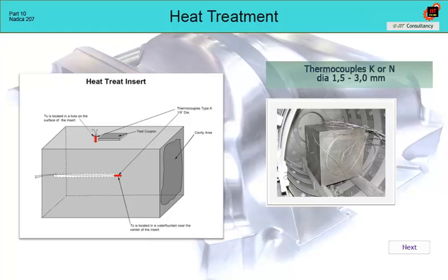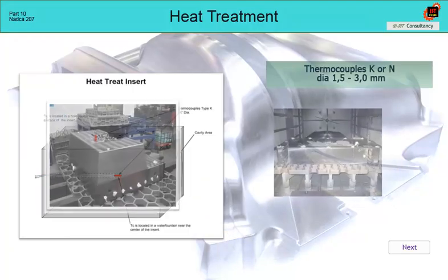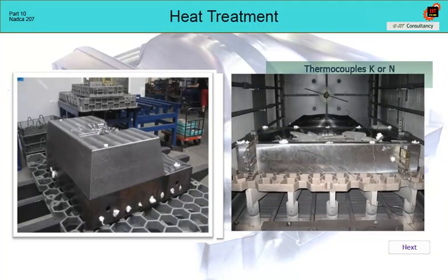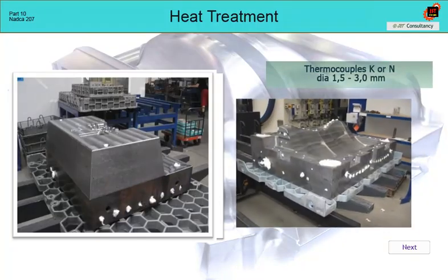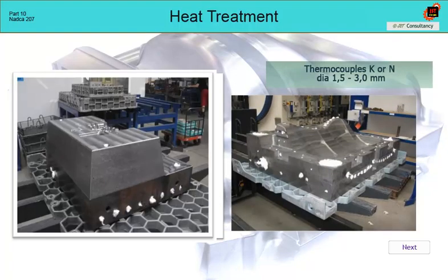A simpler situation is with the thermocouple TC, which measures the temperature of the center of the die. Usually, cooling channels or other auxiliary openings directed to the center of the part are used, but it must be ensured that in the case of a through hole, cooling gas does not flow through this hole. Glass wool, Sibral, or similar heat-resistant material is used for sealing. It must also be ensured that there is no movement of the thermocouple during hardening.